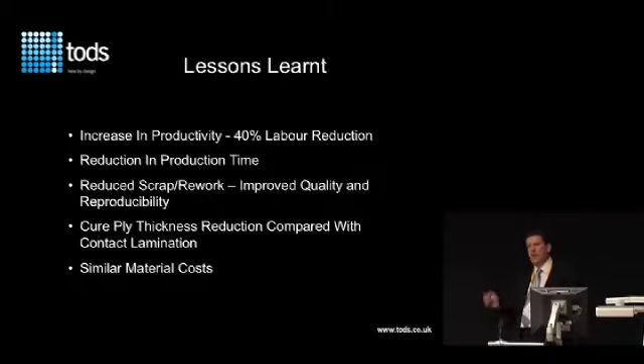We made a point of actually checking what our productivity was like compared with previous hand laminated panels, and we saw a 40% reduction in labour. I think it's fair to say the more complex your layup is, or the more stages there are, then the greater the savings. So if you're manufacturing one of these panels, obviously you need to gel coat. You would then lay down glass by hand lamination, let it cure. You'd then apply adhesive and vacuum down your foam, let it cure, and then you'd laminate over the top and let it cure. So you've got something like 5 stages, whereas with this process, you gel coat, you put your materials on, you bag and you infuse. So, as I say, basically the more complex the layup, the more potential there is for savings.